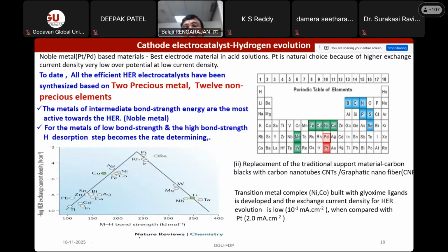And if you see the material aspects, we don't have a lot of choice for selection of material to enhance the hydrogen evolution reaction. We have about 2 precious metals and 12 non-precious metals in the periodic table to carry out these hydrogen evolution reactions. Of these, platinum and palladium are the better electrocatalyst materials for the hydrogen evolution reaction. And these, iron, cobalt, nickel, molybdenum, are all